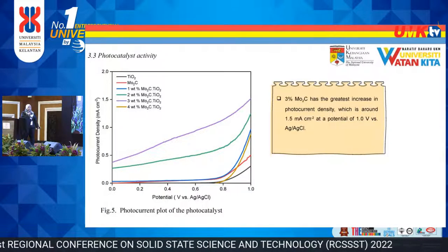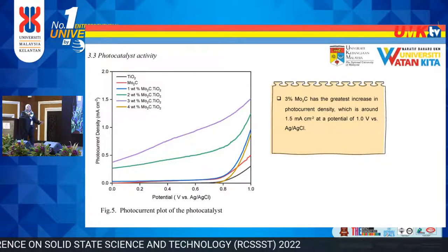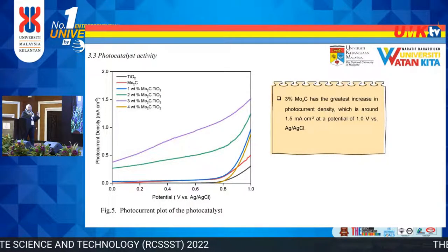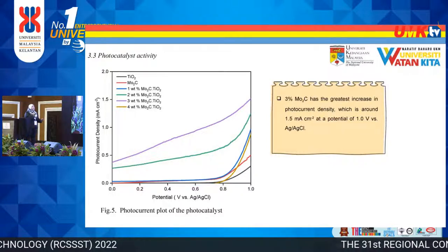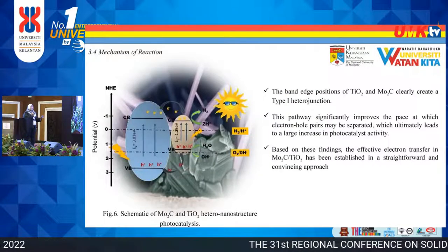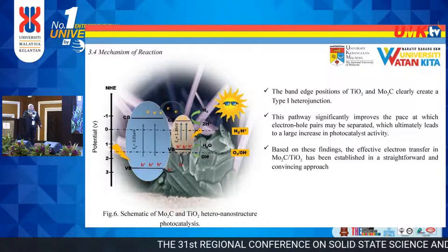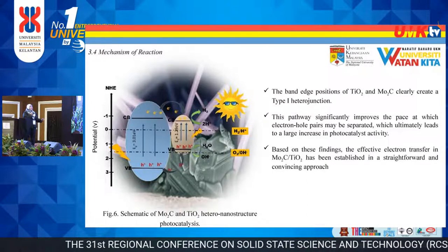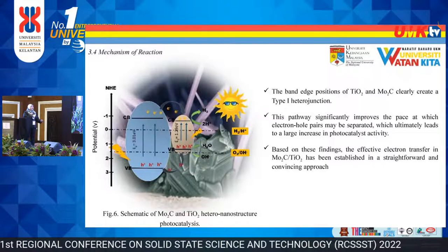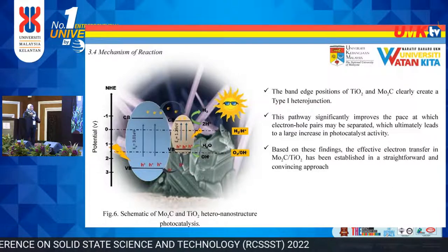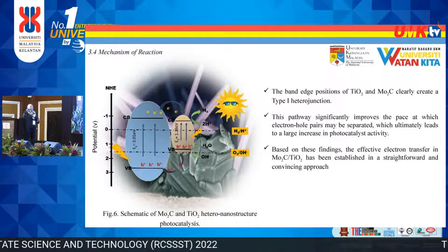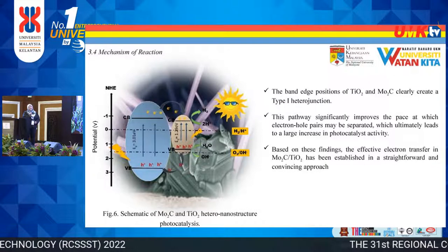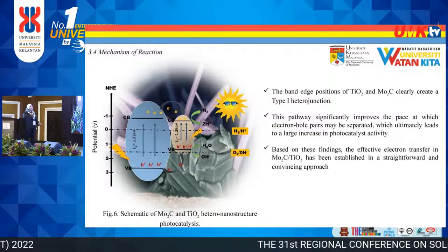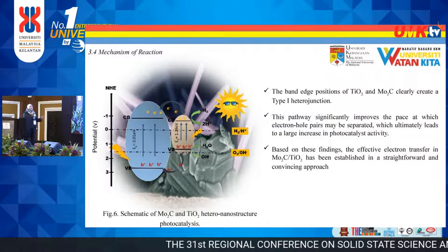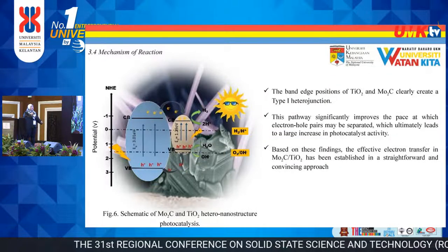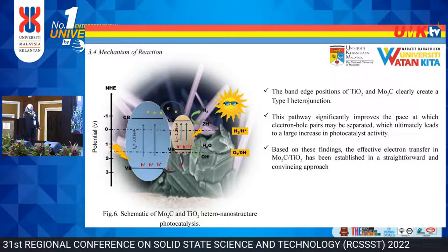So this is the mechanism of the reaction, calculated using the Mott-Schottky and with the help of the UV-Vis. From the band gap, the band edge positions of TiO2 and molybdenum carbide clearly create a type 1 heterojunction, and this pathway significantly improves the pace at which electron-hole pairs may be separated, which leads to a large increase of photocatalyst activity. Based on this finding, the effective electron transfer in molybdenum carbide and TiO2 has been established in a straightforward and convincing approach.